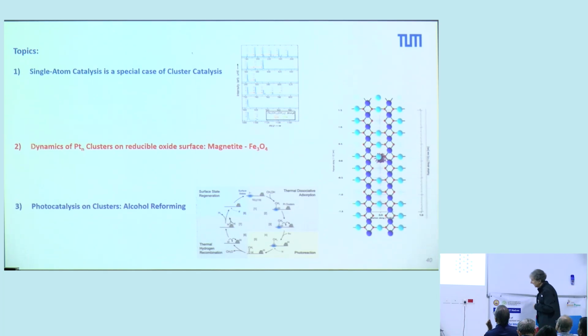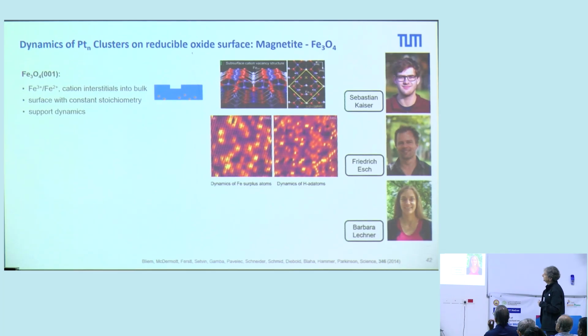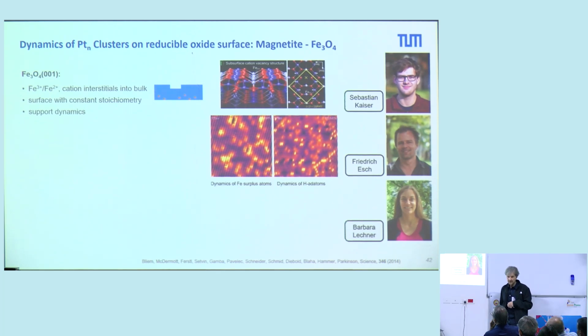And in the next example, I would like to show you the dynamics of platinum clusters on a magnetite iron oxide surface. That means we have an iron oxide surface. There are some important properties of this iron oxide, and one of these important properties is that the surface stoichiometry remains constant. That means if you are at oxidizing conditions, the iron 3+ is diffusing into the bulk to keep the stoichiometry constant at the surface. If you are at reducing conditions, it's iron 2+ which is diffusing into the bulk so that the stoichiometry remains constant.